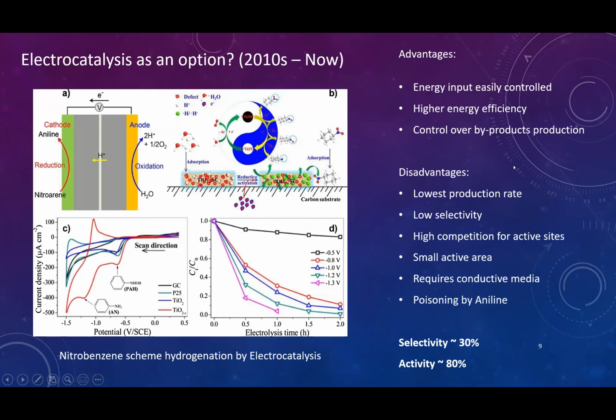When we go to electrocatalysis, we have another set of advantages. The energy input is more controlled, we have higher energy efficiency, and we can control the byproducts if we are within the working window. The disadvantages: lower production rate, low selectivity, high competition for the active sites, small active area, requires a conductive medium, and poisoning. And the selectivity is much lower, around 30%, with a conversion of 80%.